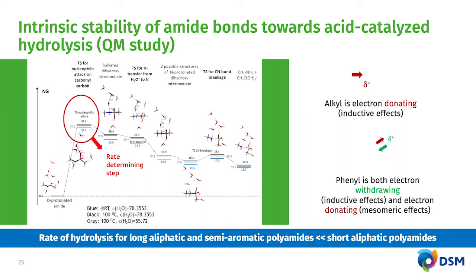In the past, we also studied the mechanisms of hydrolysis of amide and ester bonds using quantum mechanics calculations. What we do here is to theoretically predict the amount of energy needed during the whole hydrolysis process via several transition steps. It turns out that the rate-determining step, the most energetic transition step, belongs to the nucleophilic attack of the carbonyl part of the amide bonds. We use the energy needed to perform this transition step as a parameter to calculate theoretical reaction rates.